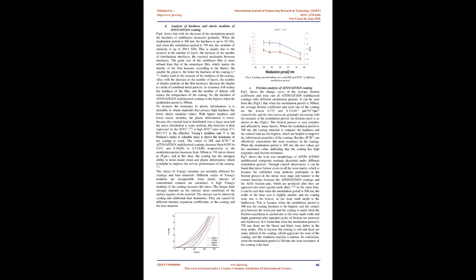In other words, the broadening of the diffraction peak indicates that the coating grains are refined. This is because, with the decrease of modulation period, the number of coating layers becomes more, the thickness of the single layer decreases, and grain growth is inhibited. It is also clear from Fig 1 that all the curves are rough. On the one hand, it is due to the large proportion of the amorphous phase in the coating. On the other hand, the multi-layer structure restricts the grain growth of the coating.